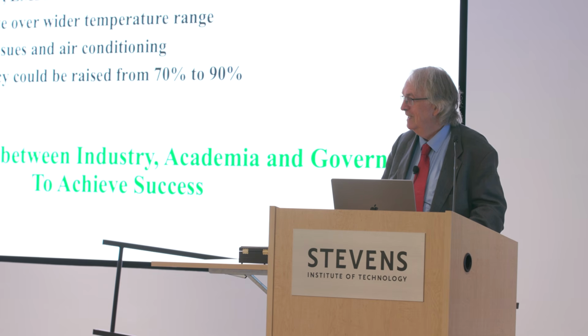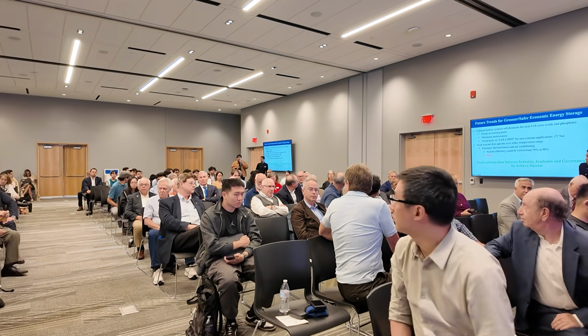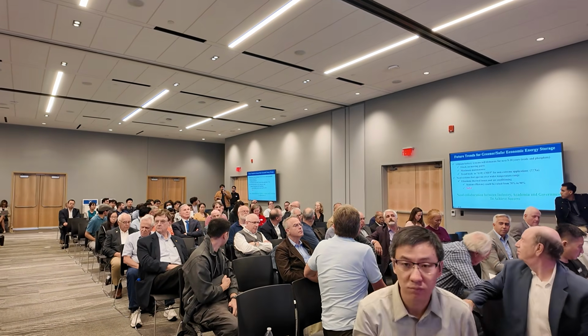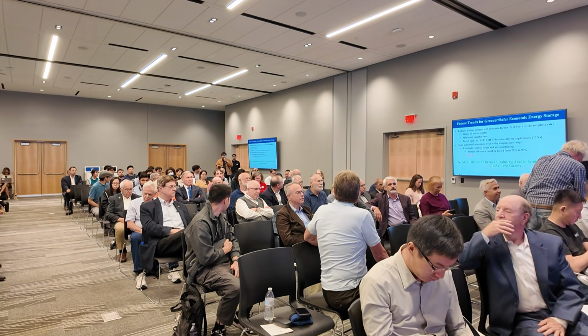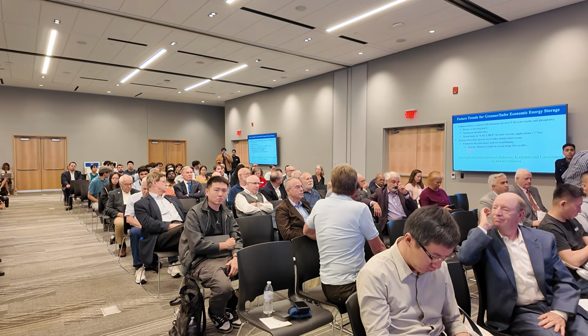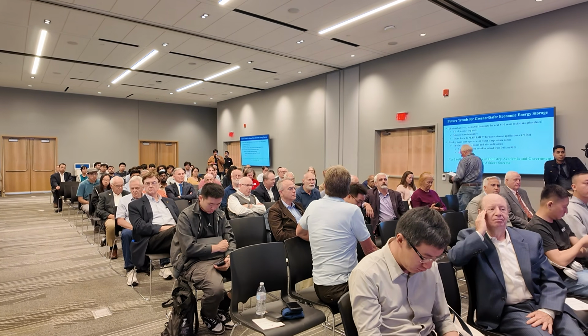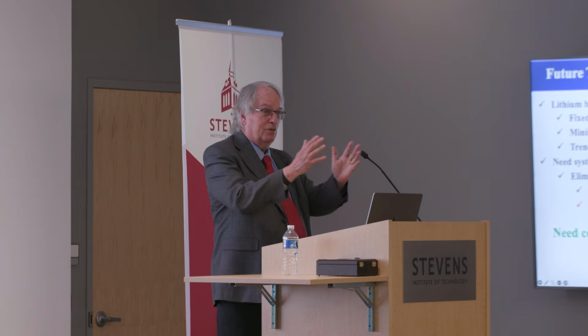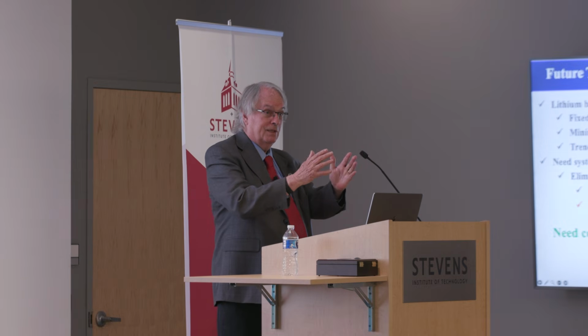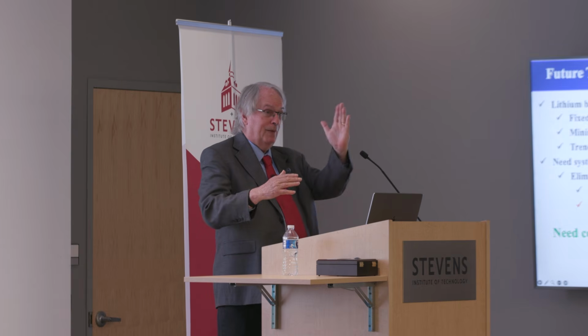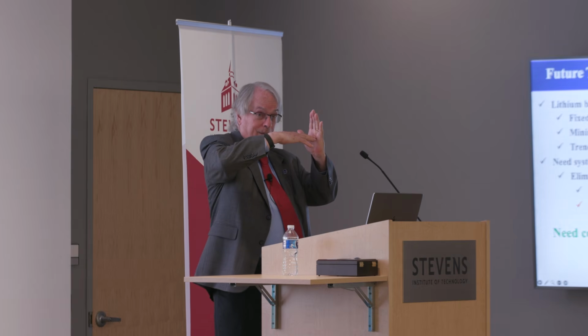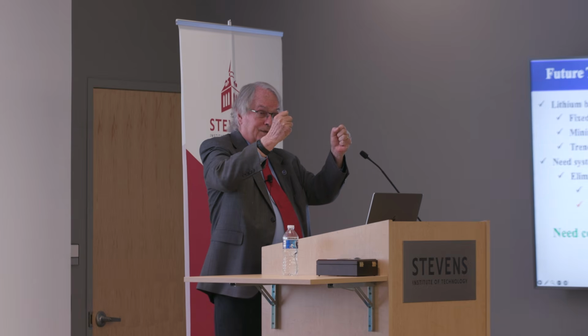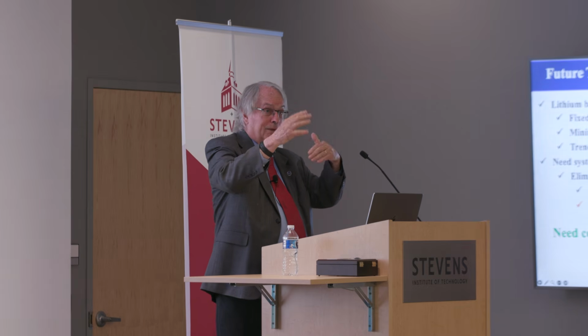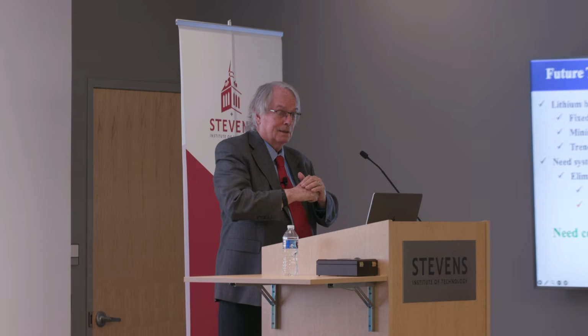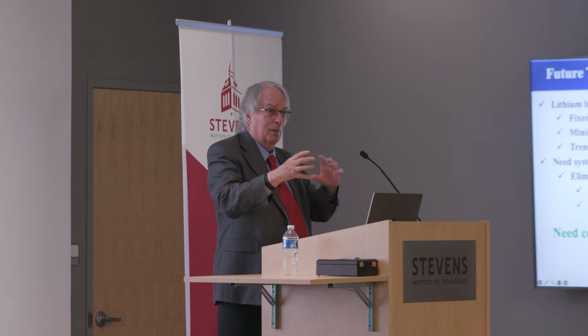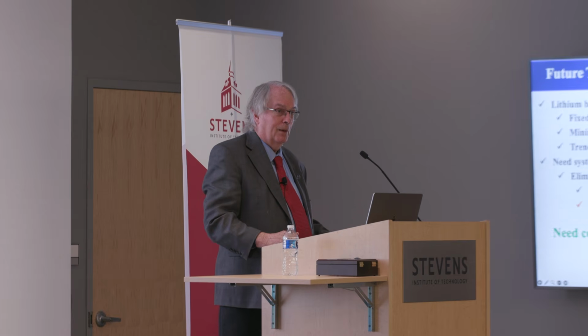Thank you so much. I remember you mentioned something like lithium's biggest problem is that as they grow, they crack. So is something like vapor deposition or any other deposition technique possible with lithium, or is it just not feasible? No. The reason it cracks is that these materials expand and contract about 10% when you charge and discharge. So you've got these meatballs, with some particles this way, some this way, so they will tend to crack if they're against each other. If they're single crystals, they tend not to crack. So it's not how you make them, it's their own morphology that causes the cracking. So we think if we keep them small enough, we paint them, we can stop the cracking.